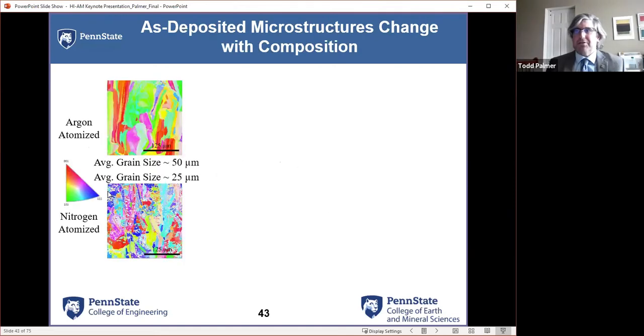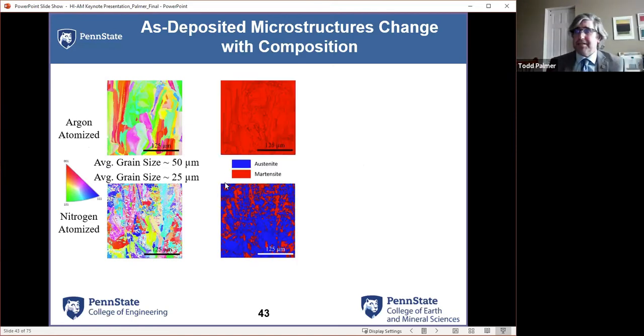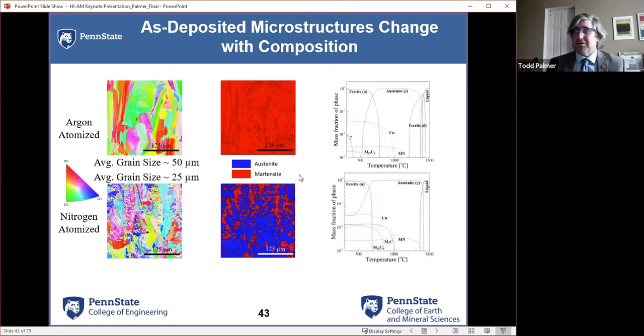As deposited microstructures can change as well. And so these are some EBSD maps and phase maps. In the argon atomized, it's almost completely martensitic. In the nitrogen atomized, it's almost completely retained austenite. And so that's sort of where these differences come in.